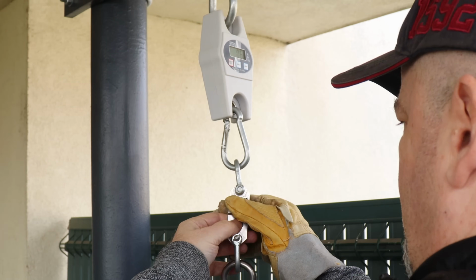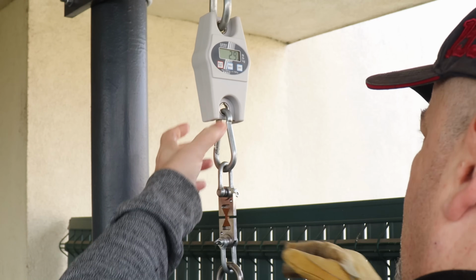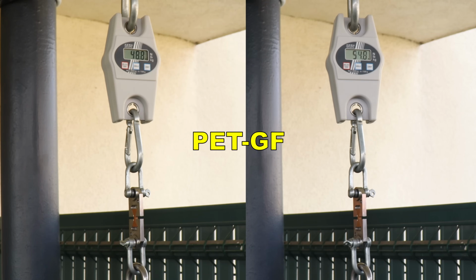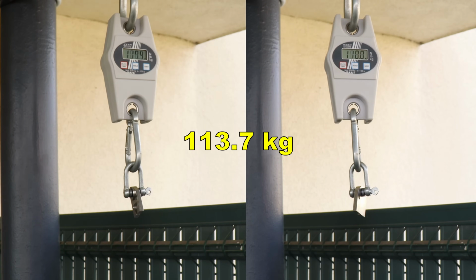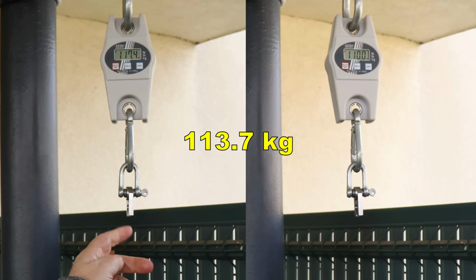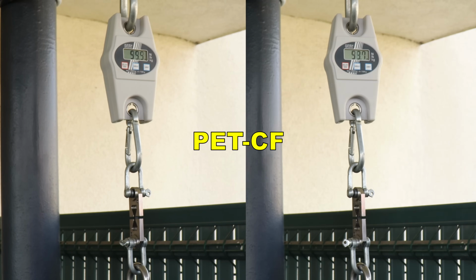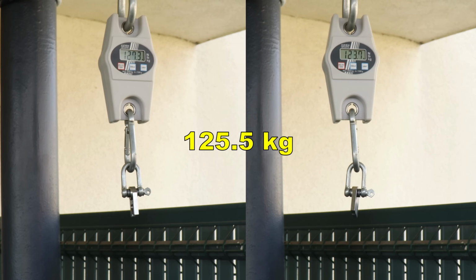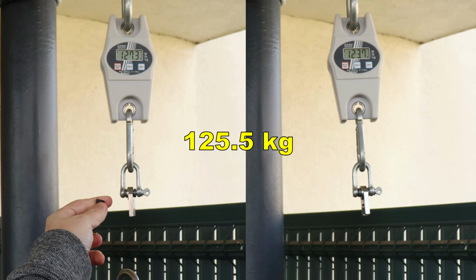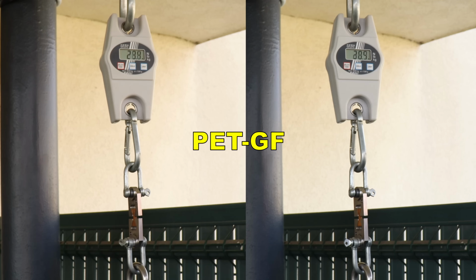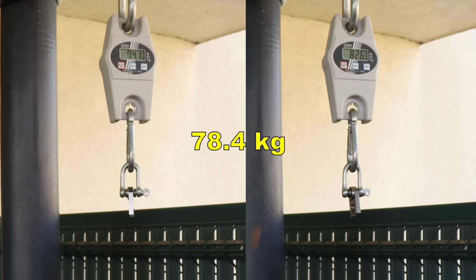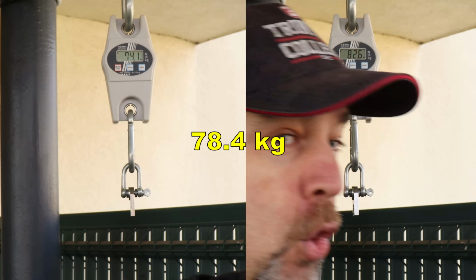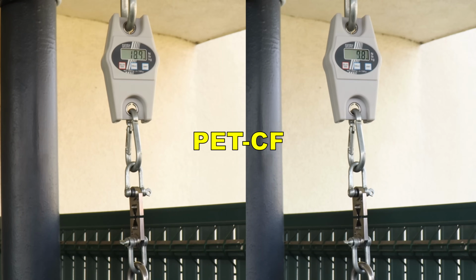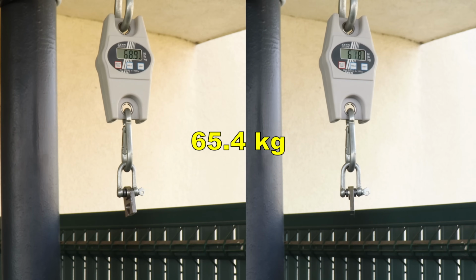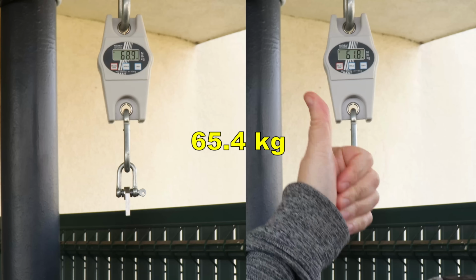I'm starting with the tensile test with the horizontally printed test objects, and this is PET-GF, and this is average from 2, and this is PET-CF, slightly stronger. And now the layer adhesion. This is incredibly good. PET-CF. This is weaker, but this is great too.